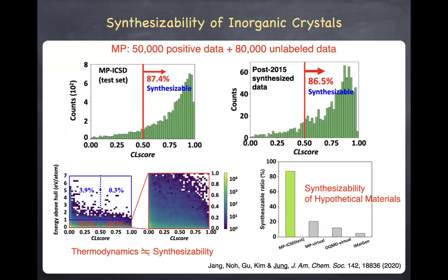And one thing that we found interesting was shown on the lower left, where we compare thermodynamics and synthesizability scores. As a computational chemist, synthesizability really is not a well-definable quantity because it could mean many different things. So we normally compute energy above hull or some kind of formation energy like energy estimations. But when we compare that, we find that even if the compounds are thermodynamically very stable, they may have low synthesizability scores. So synthesizability scores and thermodynamic metrics do not always go in parallel, although they are related in one way or the other.